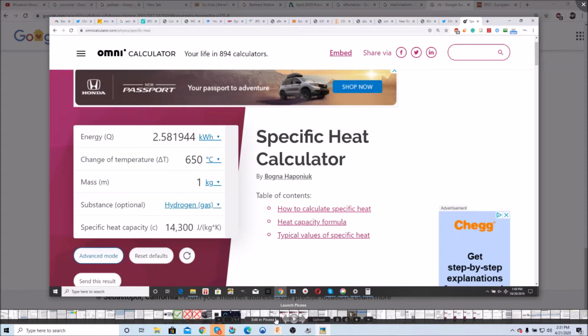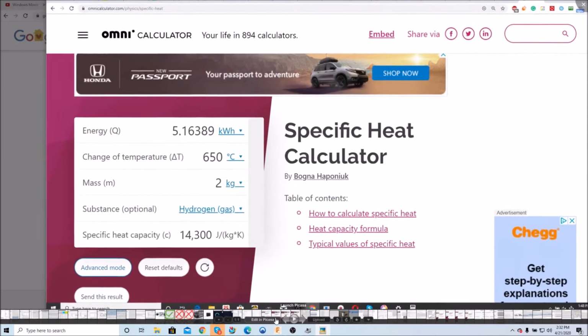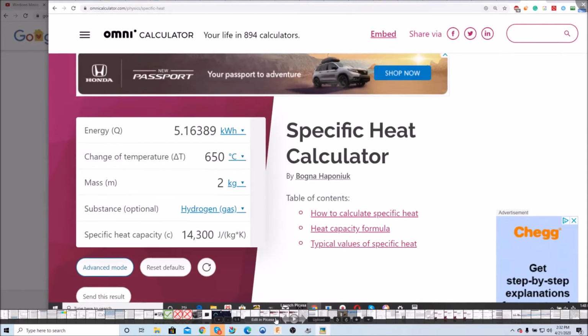we need to keep all of our catalyst channels at, let's say, 650 degrees. We know what the specific heat capacity of that particular metal is, and so we know how much energy is required to keep, let's say, 1 kilogram of that metal at 650 degrees. Then, of course, there's an additional requirement, and that is to establish how much heat is being carried away by the gases flowing through. So the hydrogen gas at high heat capacity is going to pull away a lot of heat, and so you have to take into account that heat loss from the absorption from the hydrogen, and so when you add that all up, you get around 20%.